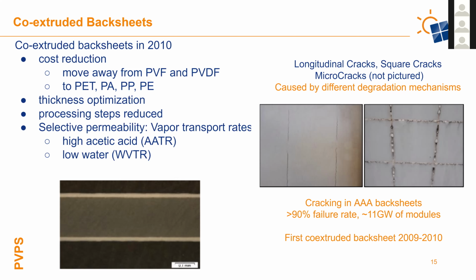We have micro cracks, not pictured here, which happen at local areas where there's a little more stress, just a tiny crack, generally on the outer air side surface of the backsheet. Longitudinal cracks happen just over the bus bars, due to a change in height over them, creating tensile stress from that slight height change, and these cracks also happen from the outside air side of the backsheet in. When we see square cracks, those happen between the cells, forming from the inside, the inner layer facing toward the sun, out of the PV module.